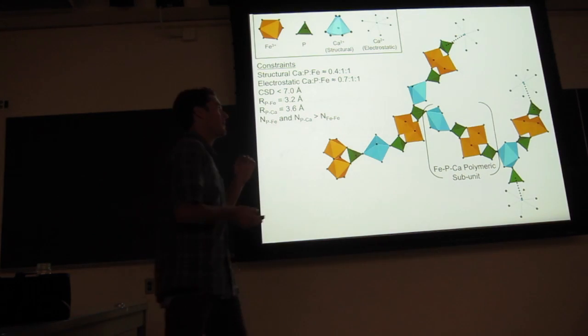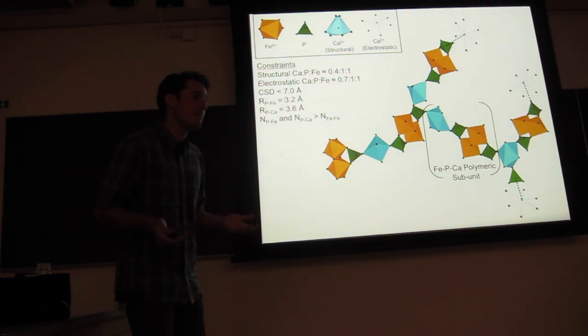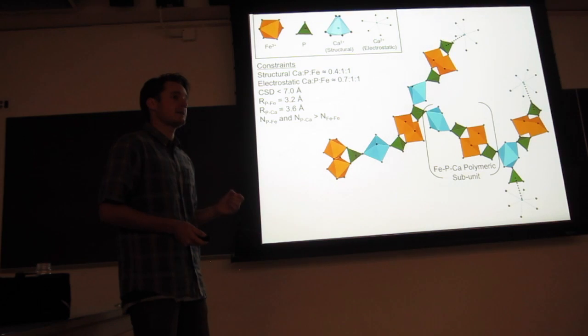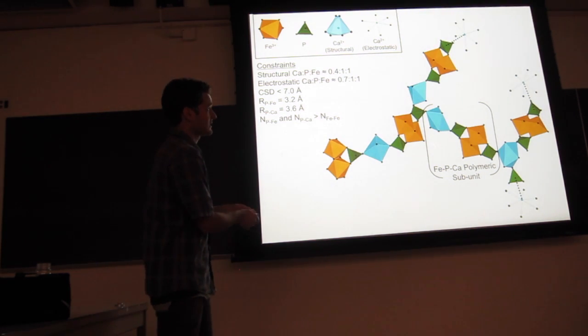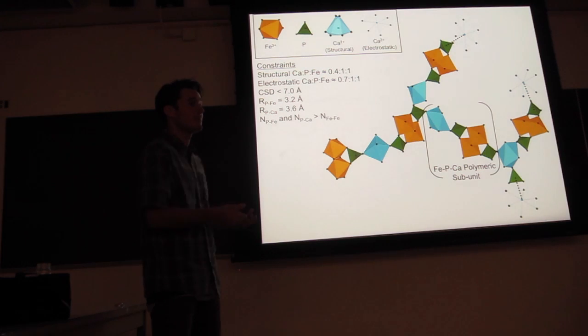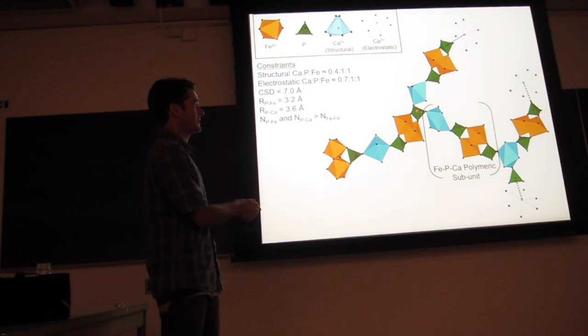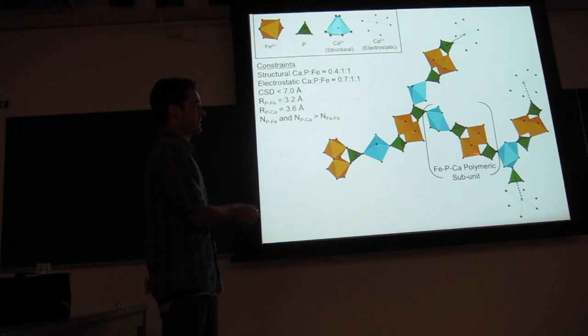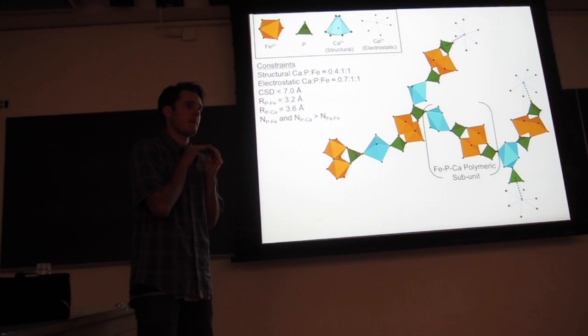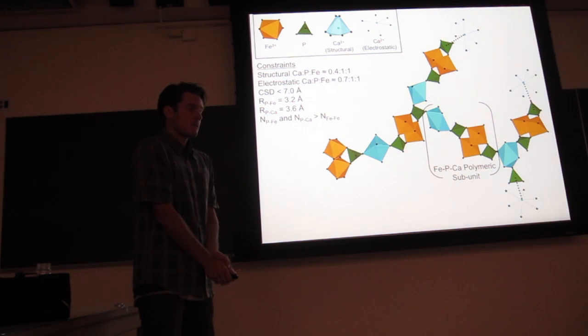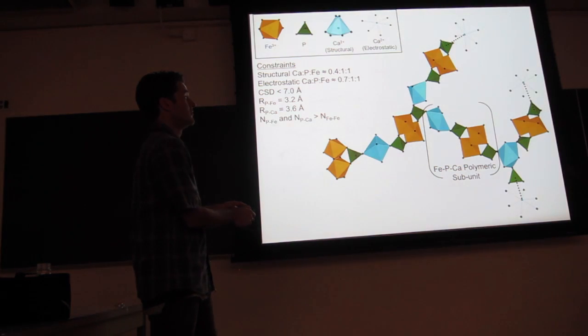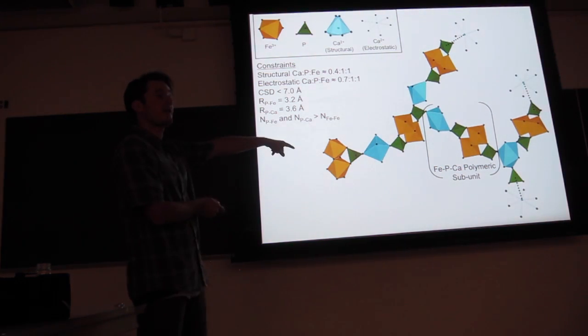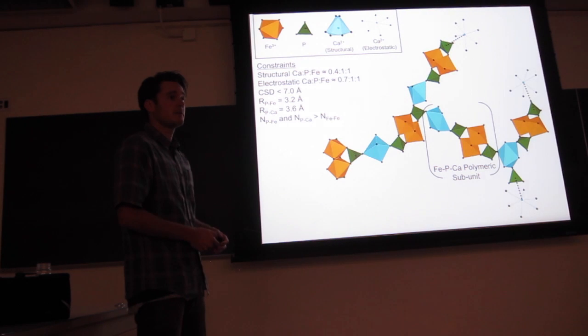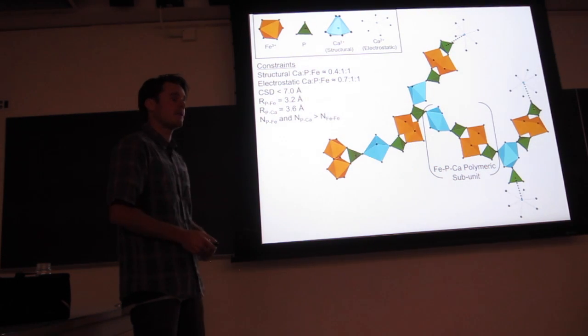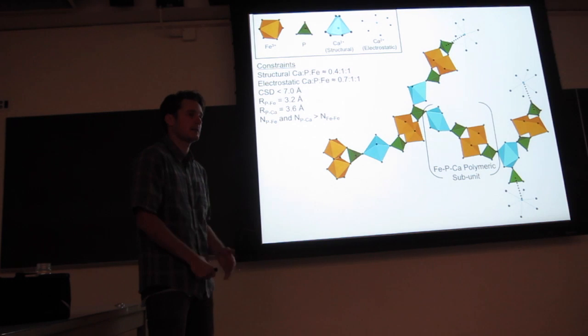The other thing is that when you have direct covalent or covalent-type bonding, that's usually a much stronger interaction than electrostatic. Right? And in this slide, you actually see that there's more spots for arsenic to bind to as well. Because arsenic can bind to calcium here and here, and then the oxide by itself, here there's no arsenic actually forming a bond. But did you see an arsenic-calcium bond in your data? No. So that's why, I mean, we're looking at phosphorus here. Oh yeah, sorry. Yeah, we did. Okay. Yeah, I assume that corner sharing, that shoulder at 3.6 angstroms.